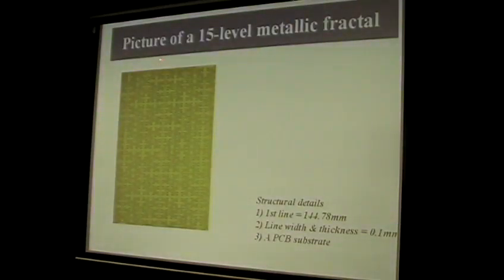This is a picture of a realistic 15-level metallic fractal that we fabricated in the laboratory. You can see that this is the first line, which is very thin, and this is some structural details. The line width and the spacing are both very tiny, and the entire structure is printed on the PCB substrate, and this gives us the whole 15-level metallic fractal plate.